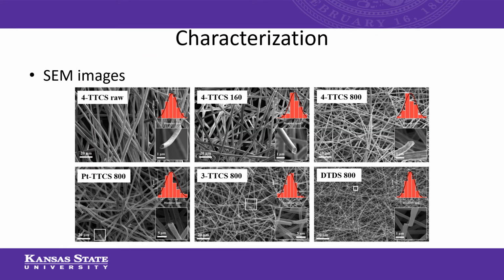Okay, let's move on to the characterization part. Here are some SEM images of our electrospun fiber mats. As you can see, the fiber diameters are very uniform, and the diameter distribution is well controlled. The average diameter ranges from approximately 2.5 down to 0.6 micrometers.